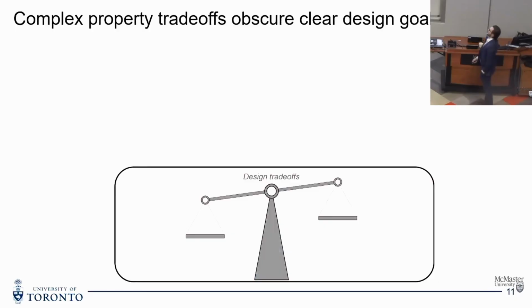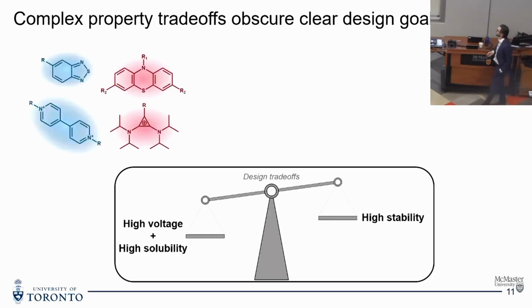Now, like any good chemical system, there are complex property trade-offs that frustrate our ability to find an optimum set of conditions or an optimum set of materials, where if we look at each of these components we've talked about, just to highlight a few examples, for our energy storage species, in this case redox active organics, we want something that gives us high voltage and high solubility. But to get high voltage, you need large energy differences between these two molecules. And as we go into more energetically unfavorable states, where we get these high voltages, we compromise stability, as again, these are not favorable conditions for molecules. So we often have to balance high energy with high stability.